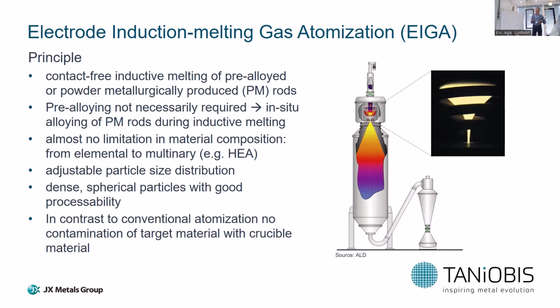Accordingly, since you can start with PM rods, with powder mixtures, you have almost no limitations in material compositions. So you can start with either elemental powders and go up to master alloys. Depending on the process parameters, you can adjust the particle size and particle size distribution. Usually, we obtain dense spherical particles with good processability. And as I mentioned, in contrast to conventional atomization, there is no contamination of the powder with a crucible material.